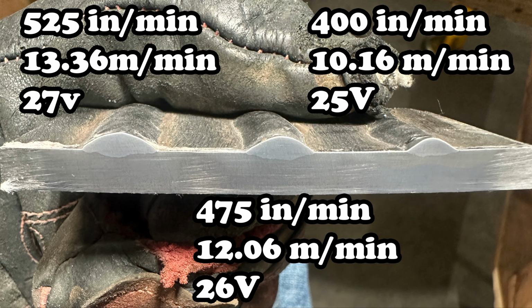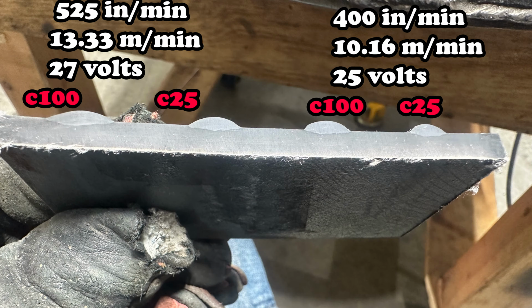Well, let's look at the C25 versus C100 comparison. So here we go, comparison between C25 and C100. The gas mixture is above each weld. At the lower values, we can see not a huge difference between them. Honestly, depending on where I did the cut and etch, it might have been a toss-up. So the C100, shockingly enough, does not appear to have as much of a difference on this wire as it does with hard wire in the short circuit process. It made a huge difference in root penetration.